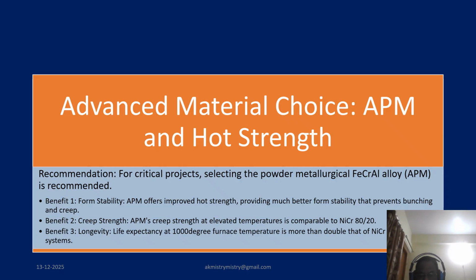So thus, for maximum assurance, we must select the powder metallurgical iron-chromium-aluminum alloy APM. APM offers improved hot strength, resulting in better form stability that actively prevents bunching and creep both. The creep strength of APM at elevated temperature is comparable to nickel chromium 80-20. This advanced material provides longevity, resulting in a life expectancy at 1000 degrees centigrade that is more than double that of nickel chromium wire.